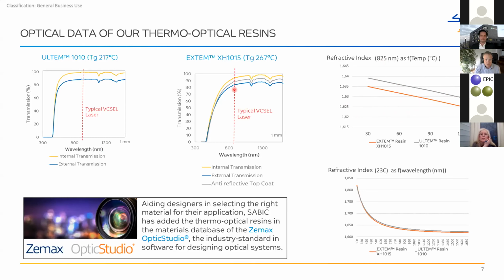Here's the transmission again. I mentioned 80%. That's what you see here on 1 millimeter of Extem. If you really want to increase that, think about LiDAR, for instance, where every photon counts, you can apply an anti-reflective coating. So if you put one coating on top of the lens, you increase the transmission by 5%. If you are able to also apply a coating on the bottom of the lens, then you go all the way up to 91%. It's still not like Ultem or polycarbonate or glass, but it's pretty high.